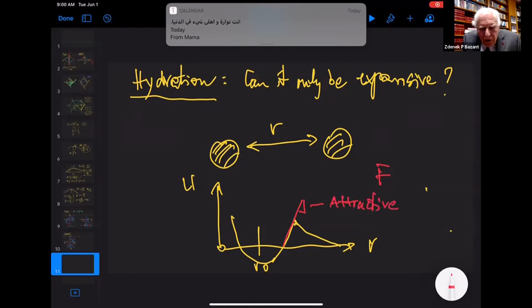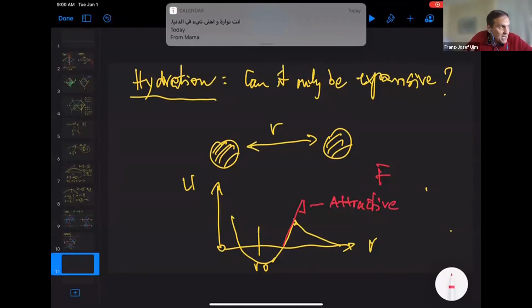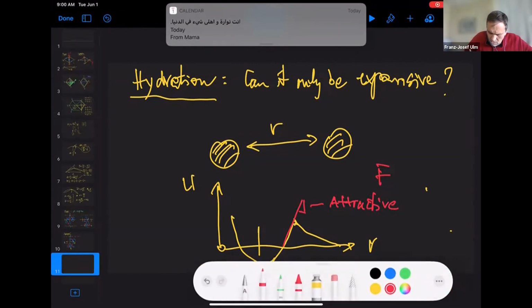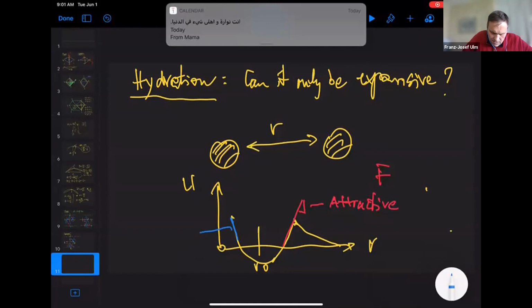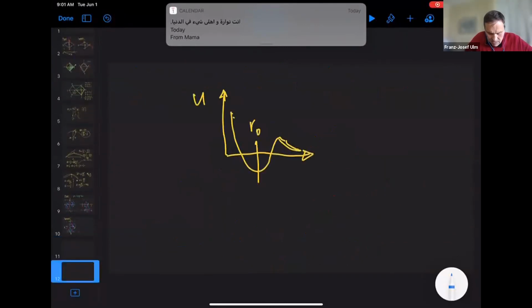These are grains, right? Or material atoms or molecules? Grains, CSH grains. I'm talking about scales of 5 nanometers with high surface factors, whereas on the other side here, you have some repulsion. Now, why is that important? Because when I think about the hydration, you start out, of course, hydrating into an empty space. So at some stage, I start out from here. This is my distance R. I hydrate here with a distance which is relatively large. So here, there's clearly a repulsion taking place.